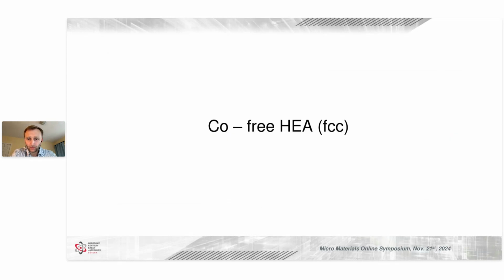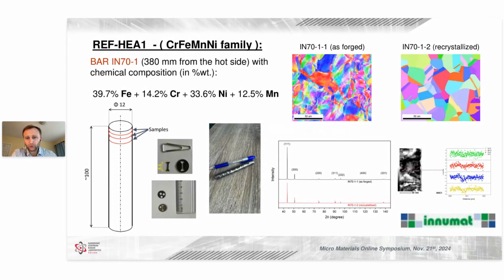So quickly, I will tell you about two examples of high entropy alloys we are studying right now. I will start with a demonstration that by doing macroscopic tests, we can get similar results as with nanoindentation. This work is being done in a European collaboration called INNUMAT, where we are developing cobalt-free high entropy alloys, whose application will be in next generation nuclear reactors. In this work, we are doing high temperature tensile tests on miniaturized dog bone specimens; you see in the image here that we are testing 8.6 millimeter length dog bone specimens.